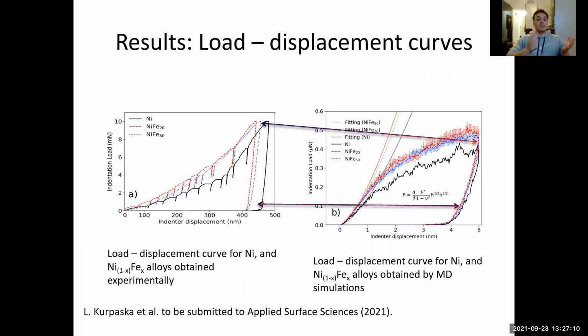So what are the results? As I said, in the MD simulations and in the experiments, they have the load displacement graphs, but now we need to analyze and see what is the corresponding, back-to-back relationship. Now here, this is the result from the experiments. I'm going to show only nickel and nickel iron 20 and 50%. When they are doing the nanoindentation test, they have an initial load, and then they practically don't know where the maximum depth is. They actually can know because there is a correspondence with the initial load, but it's a little bit difficult to track.